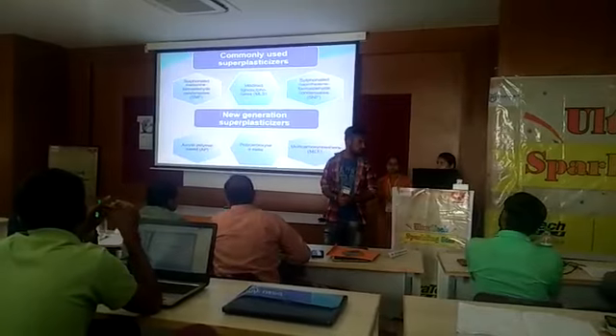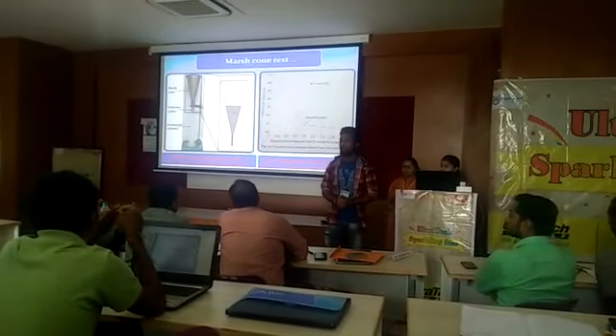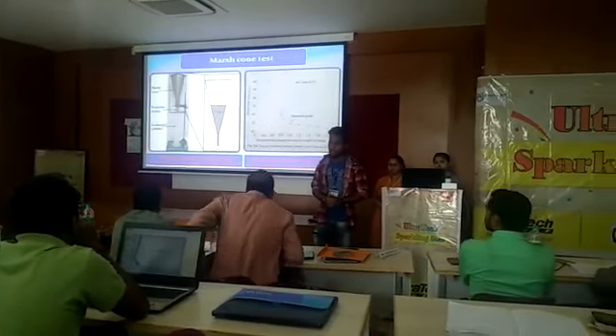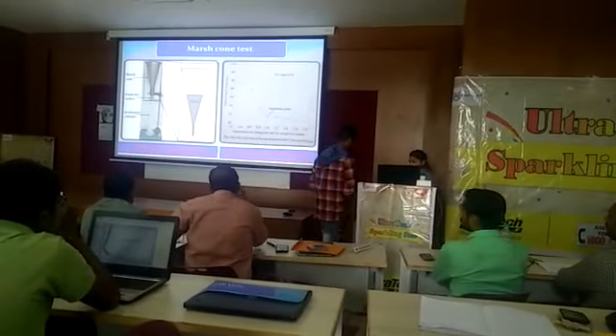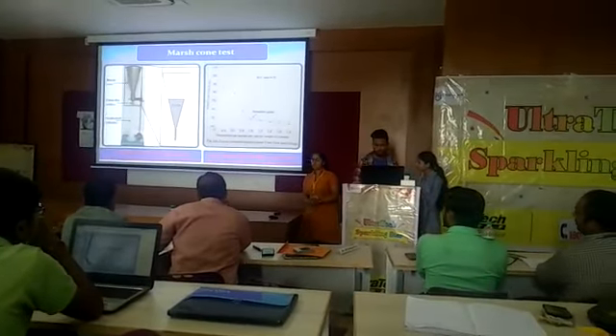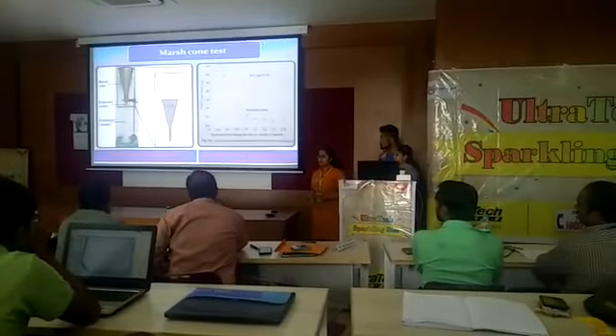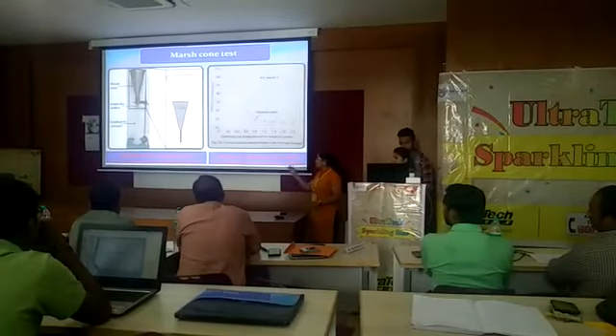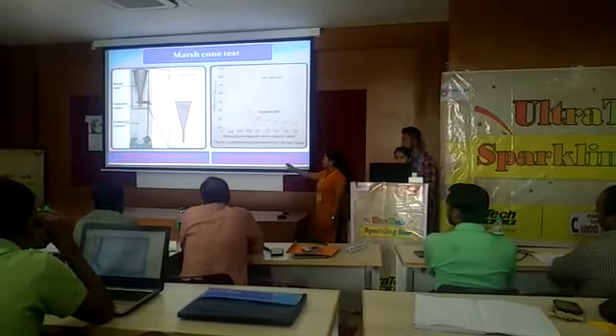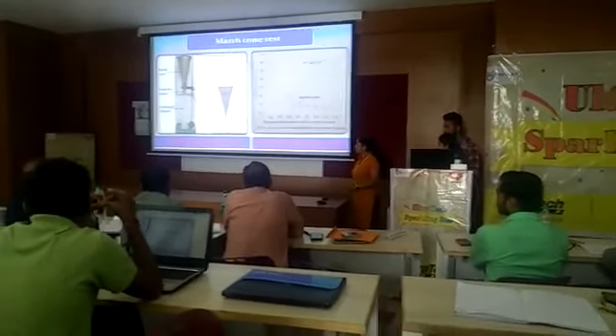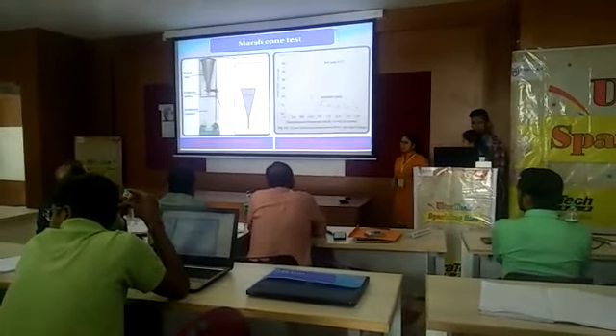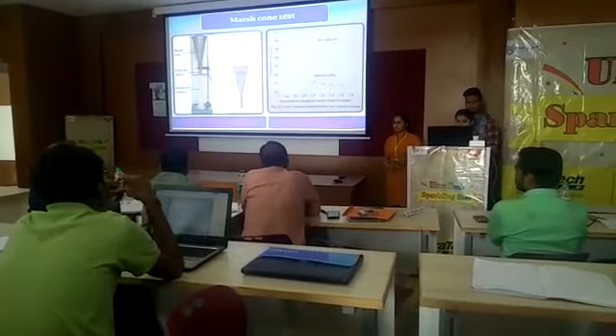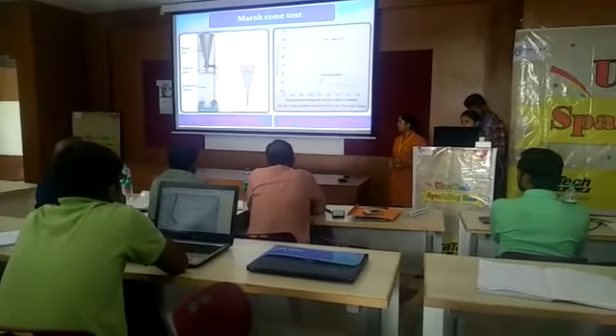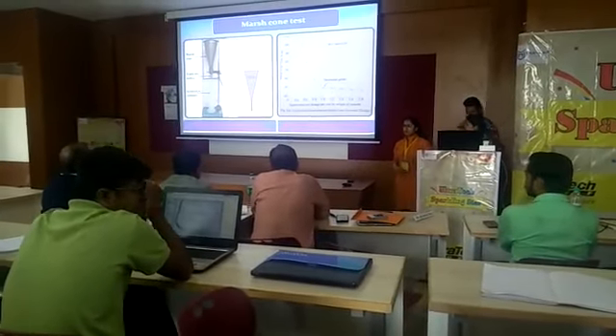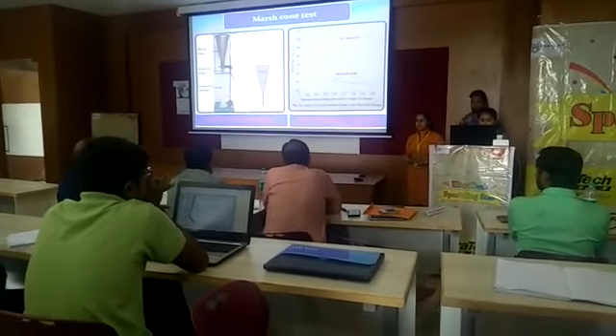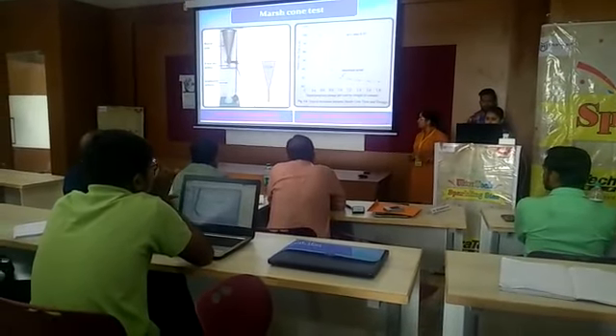Now my friend Purna will tell you about further admixtures in detail. We'll see about the Marsh cone test, which is conducted for deciding the dosage of a plasticizer or superplasticizer. Here is the apparatus showing a conical vessel, a graduated cylinder and a Marsh cone. The procedure is: take 2 kg cement and 1 liter of water. Keep the water cement ratio at 0.5. Take about 0.1% of plasticizer and mix the slurry in a mechanical mixer for about 2 minutes.